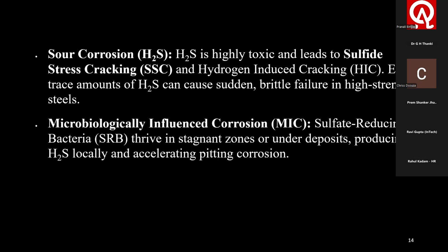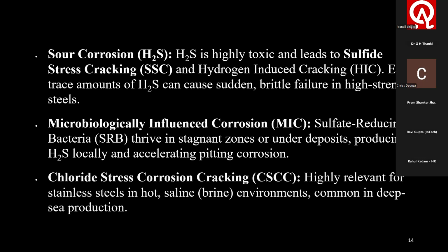Microbiologically induced corrosion, MIC, as we fondly call it. Sulfate reducing bacteria thrive in stagnant zones or under deposits, producing hydrogen sulfide locally and accelerating pitting corrosion.